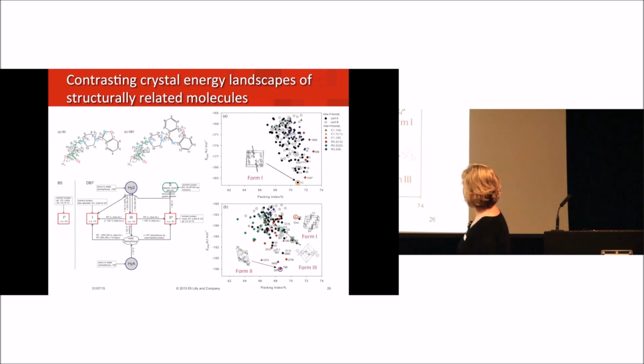With Sally and Doris Brown's help, we were able to come up with a structural model. Actually, they were able to do that for one of the compounds that we could not get single crystal structures of because this was a dehydrated species. But what you can see here is in this comparison, and here's your Z prime of one answer, if you're looking at whether you would expect monomorphism or polymorphism, you're not seeing a decided difference between these two. And so it's what we're learning in the process of this research collaboration is how to interpret these crystal energy landscapes in light of what we are seeing experimentally.